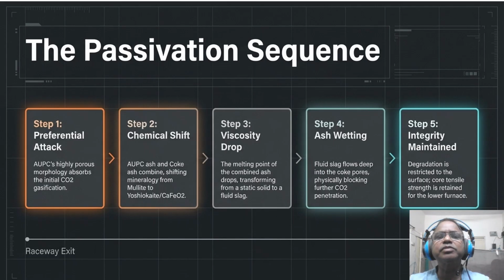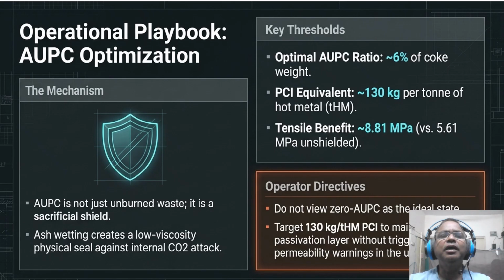So what does this mean for your next shift? Here is the playbook. This operational playbook is about AUPC optimization. So here is your key takeaway. Stop viewing AUPC as just waste material. With that in mind, our target should be at least a 6% AUPC ratio, which is equivalent to roughly 130 kg per ton of hot metal. So our goal is a tensile benefit of 8.8 MPa.